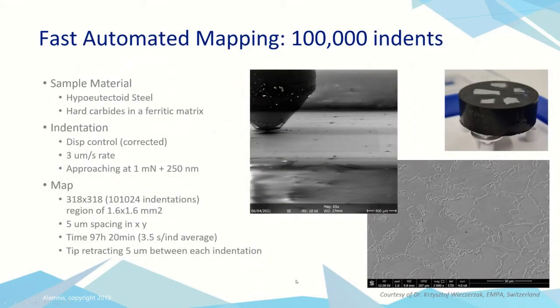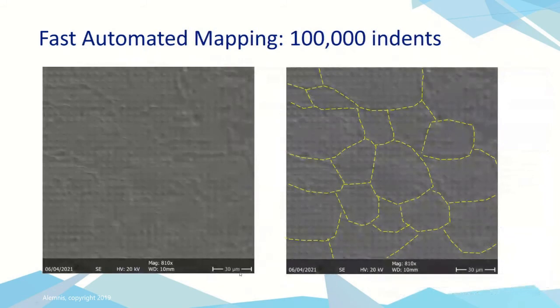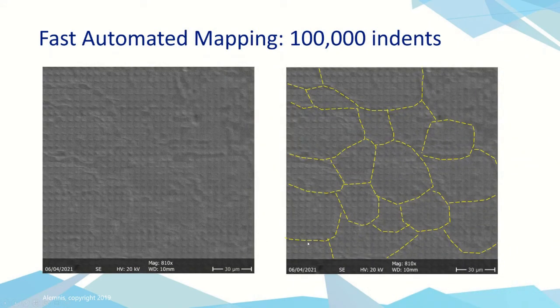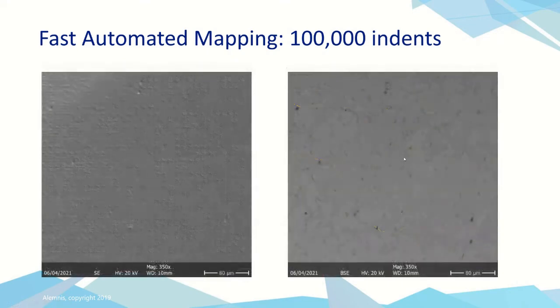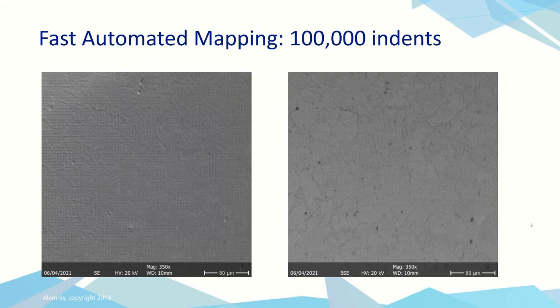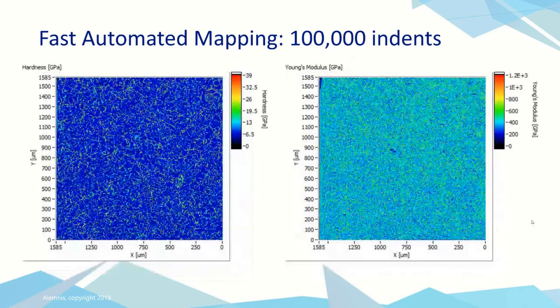This is an indent map of 100,000 indents on a steel surface. And you can see here what the indents look like, and we can still see with the secondary electron image the grain structure of that material. And here we can see the backscatter image in addition to the secondary electrons. And here we can see the maps that are generated there.